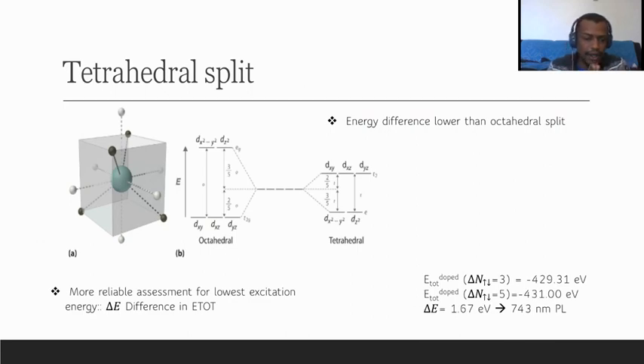to be able to understand the excitation, we use a more reliable assessment, which is the energy difference, just the delta energy in the total energies of the ground state of the doped model and the excited state of the doped model. So we did the difference, and it corresponded to a band gap of around 1.67, which corresponds to an emission of about 743 nanometers, which is closer to the emission that we saw experimentally. Next slide, please.